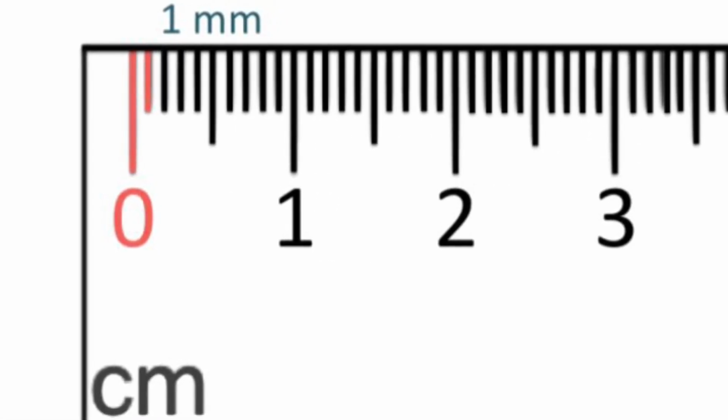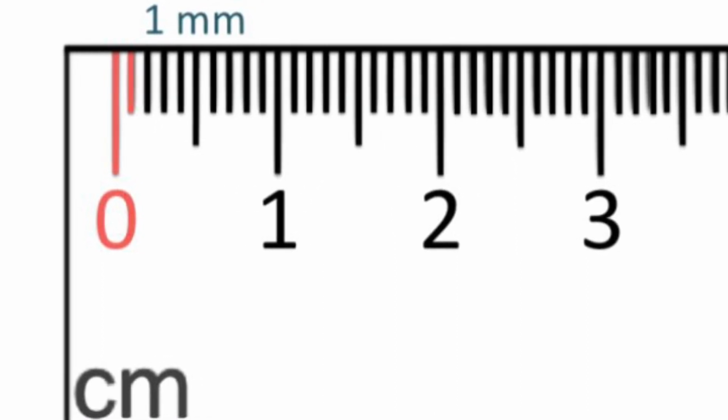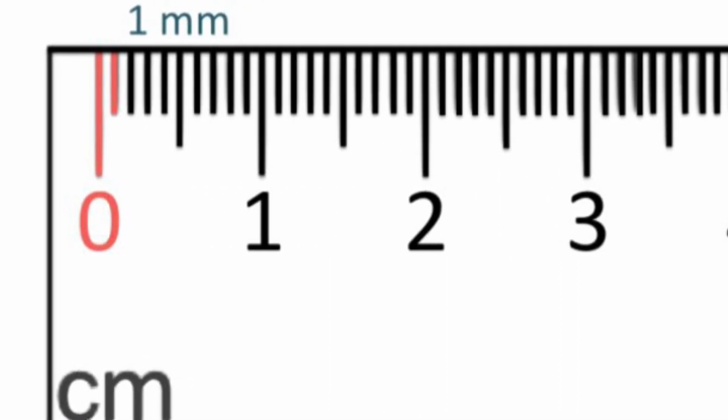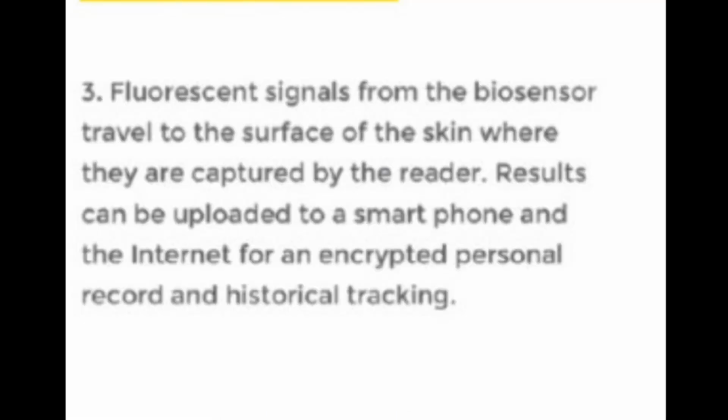I believe it's 60% porous, and it's implanted 8 millimeters below the skin surface, so it's measuring interstitial fluid. Yeah, that's correct. 8 millimeters is like the height of 4 nickels stacked on top of each other. It's about 60 to 70% porous. There are a couple of features of the sensor that we've engineered so that it can overcome that foreign body response, because the foreign body response really is the key barrier for long-term continuous sensing, as it's been attempted for the last half a century.